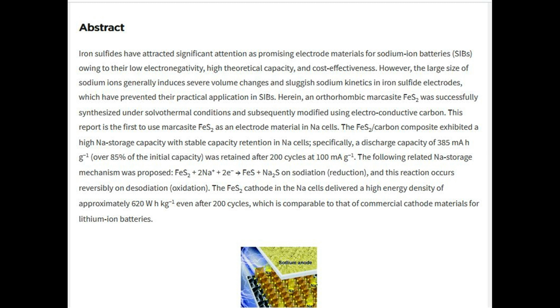The FeS2/carbon composite exhibited a high Na storage capacity with stable capacity retention in Na cells, specifically, a discharge capacity of 385 mAh/g, over 85% of the initial capacity, was retained after 200 cycles at 100 mA/g. The following related Na storage mechanism was proposed: FeS2 + 2Na+ + 2e- ⇌ FeS + Na2S on sodiation, reduction, and this reaction occurs reversibly on desodiation, oxidation. The FeS2 cathode in the Na cells delivered a high energy density of approximately 620 Wh/kg even after 200 cycles, which is comparable to that of commercial cathode materials for lithium-ion batteries.